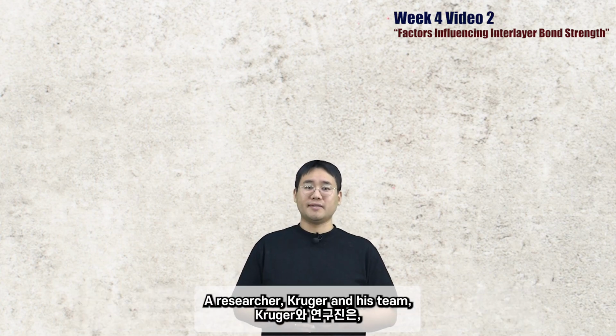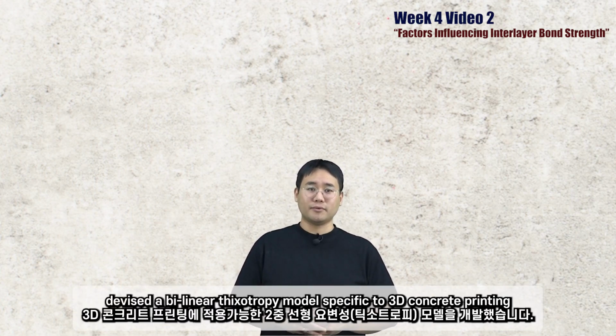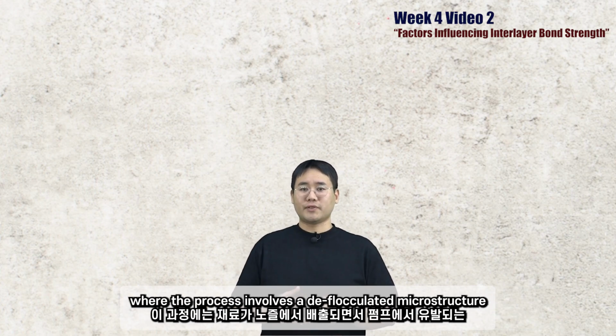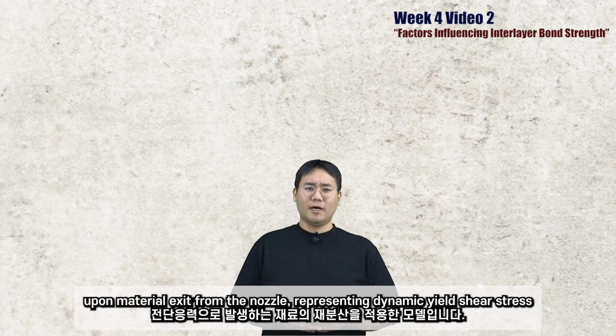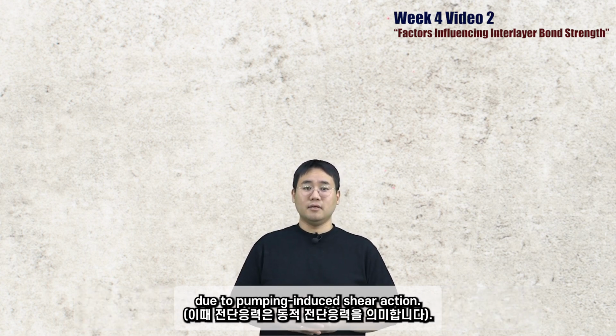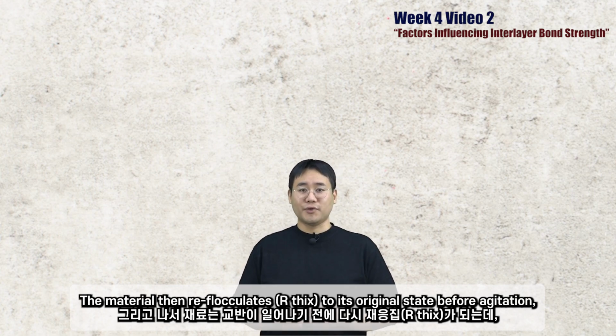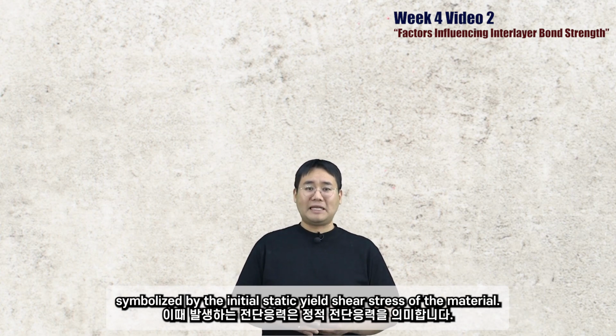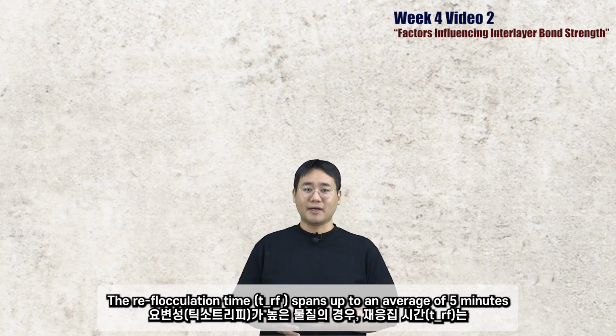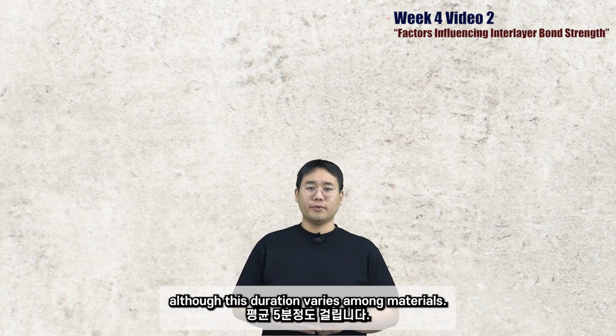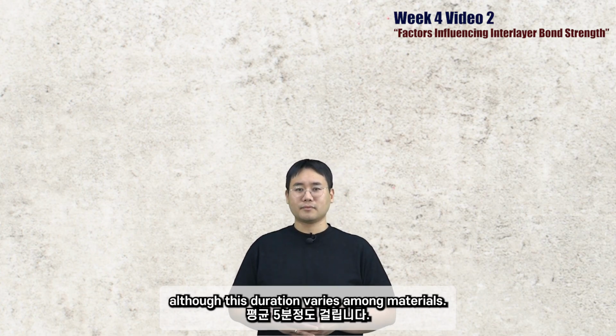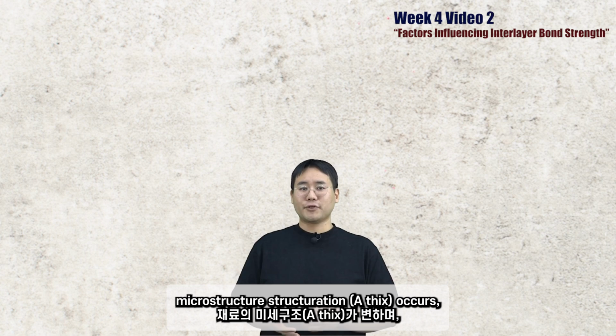A researcher, Kruger, and his team devised a bilinear thixotropy model specific for 3D concrete printing, where the process involves a deflocculated microstructure upon material exit from the nozzle, which represents the dynamic yield shear stress due to pumping-induced shear action. The material then reflocculates to its original state before agitation, symbolized by the initial static yield shear stress of the material. The reflocculation time spans up to an average of 5 minutes for highly thixotropic materials, although this duration varies among materials.